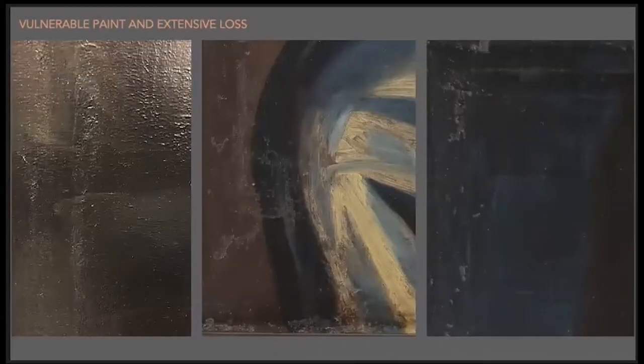Due to the failure of the wax resin to consolidate adhesion between ground and paint layers, there was localized raised paint that required stabilization, and loss that was visually disruptive. On the far left, a raking light image shows sharp, tenting, and cut paint that is lifting from the canvas support. Wax is highly responsive to changes in humidity and temperature, allowing for this movement over a long period of time. Many of the losses were old, and some had not been filled or retouched, depending upon where they were located in the composition.